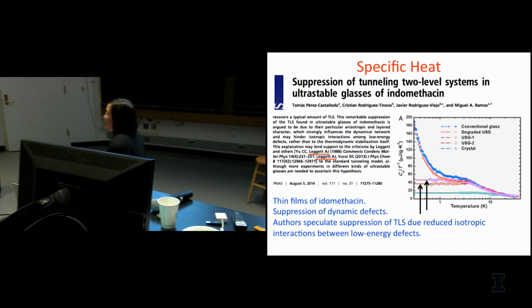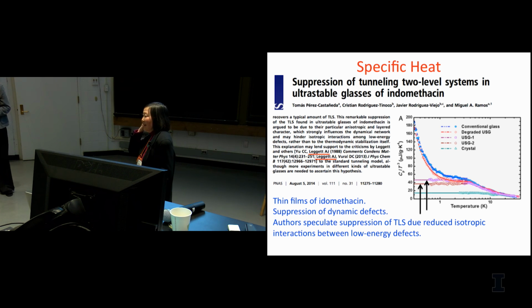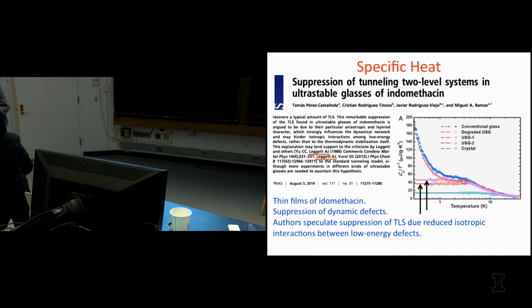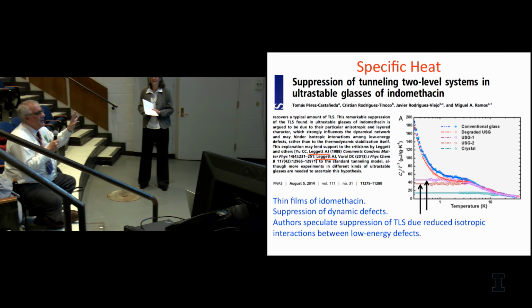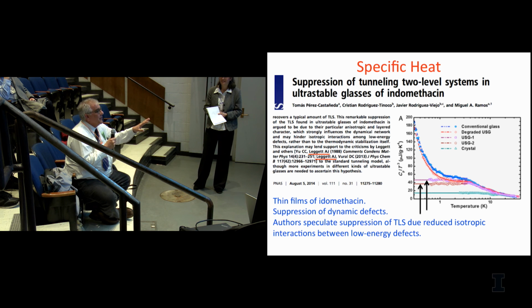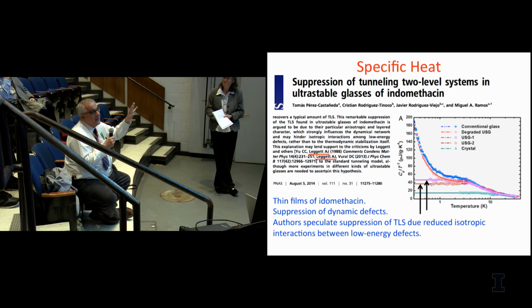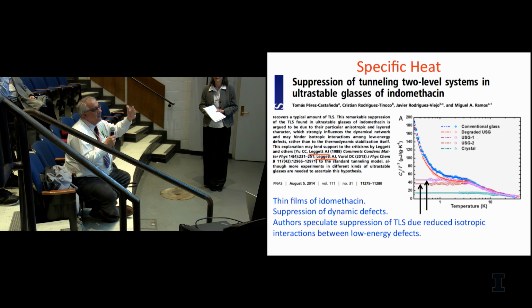Peter? This is more in the way of a comment. First of all, in my view, and in Vassilchenko's view, the L over lambda equals 150 has been explained by the scenario we present. It's roughly the size of one of these regions, and it does cancel out because of this correlation of TG. This particular experiment on indomethacin, I hope people do more of it. These are so-called ultra-stable glasses, and they're at a lower effective TG, and their correlation length has been doubled, roughly speaking. And that then means in densities that you're down by a factor of 10. At least in emails, they say that's probably consistent with their data, but they wouldn't say it proves it.